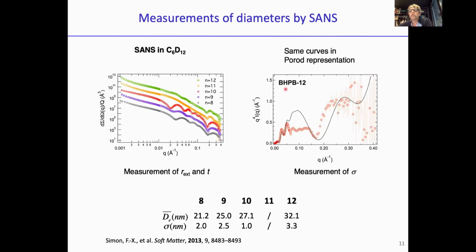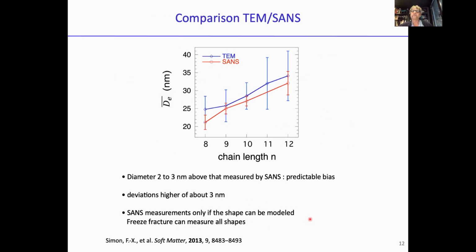And here is an example where the nanotubes are polydispersed. And you can see what I was telling, that the oscillations tend to be attenuated when you compare it with the theoretical form factor. So from this neutron scattering, we're able to also measure the outer diameter and also the real polydispersity. And what was interesting is to compare it with the freeze fracture.